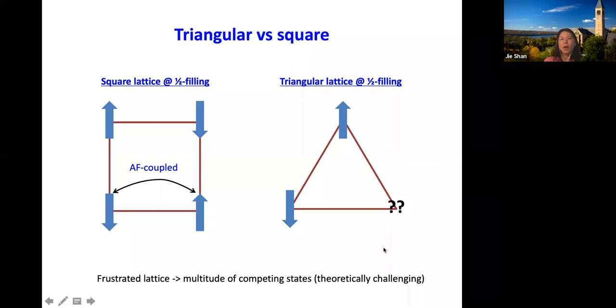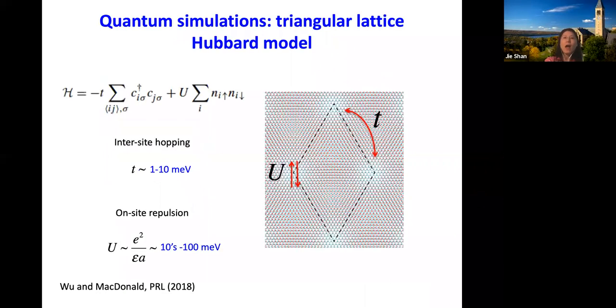So far I've only talked about filling factor equals 1, half filling. But what happens if you dope the Moire insulator away from half filling? You can easily imagine the problem becomes very complicated. So having a physical system, as I said before, that can realize the Hubbard model is really helpful. We can tune the filling factor by changing electrostatic gating. And this interlayer hopping depends pretty much exponentially on the twist angle. So you can tune U over T, or you can come up with a screening scheme and tune U over T. So in principle, you can tune U over T over a very large range, and also the filling factor.